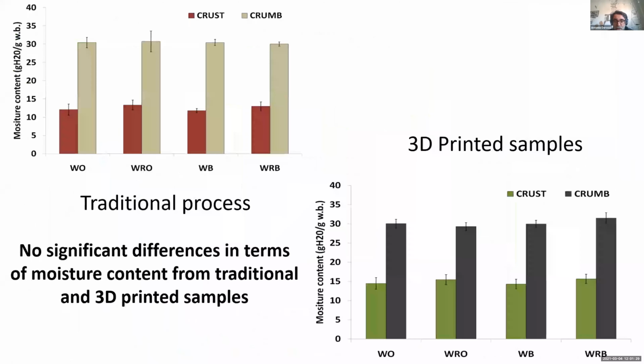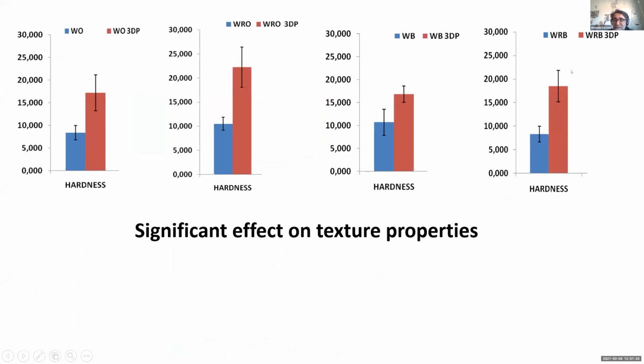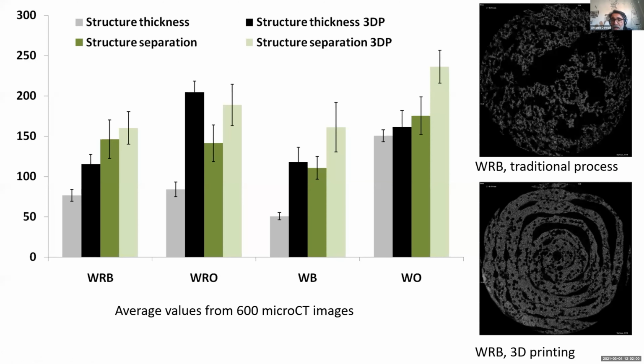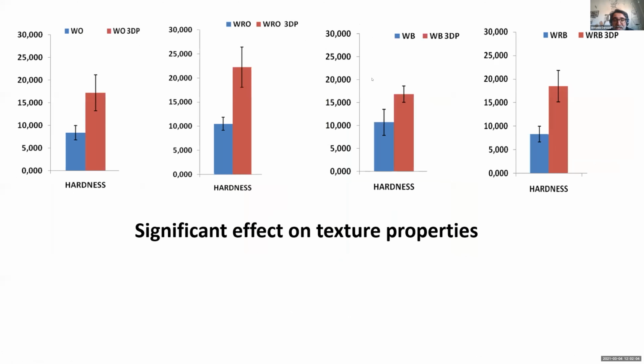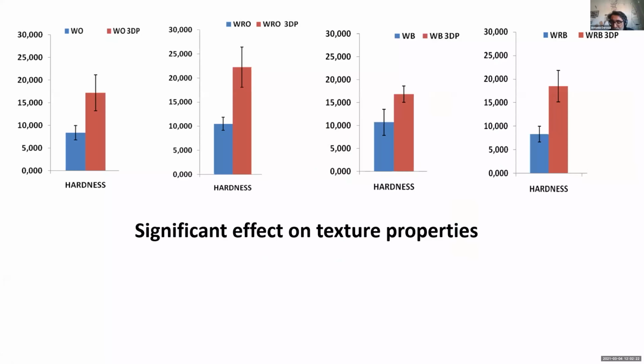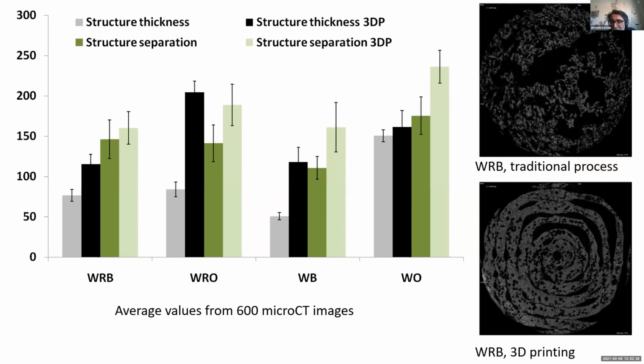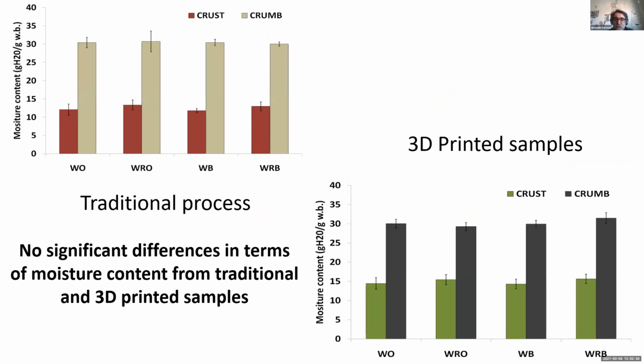And also, this is the hardness. We can see that the hardness of the 3D printed sample is higher than the control sample. And the last point was to, again, take one part of this microstructure image and try to model this by COMSOL, by finite element method. And we can see that the experimental stress, in a very small portion of the 3D printed snack, was 2.23, and we obtained an estimated stress of 2.45. So we can also use the microstructure image that acquires specifically what's happened inside the filament to obtain a better validation and a better estimation of texture property.